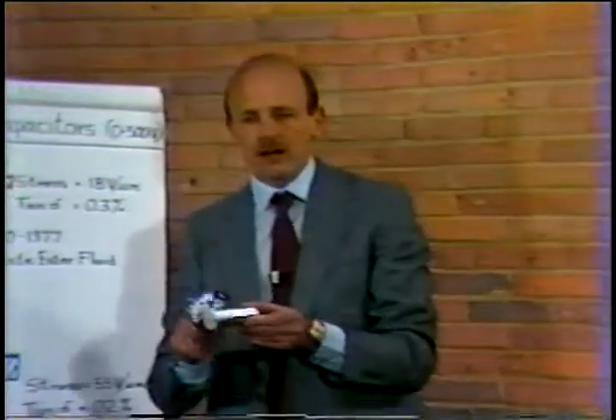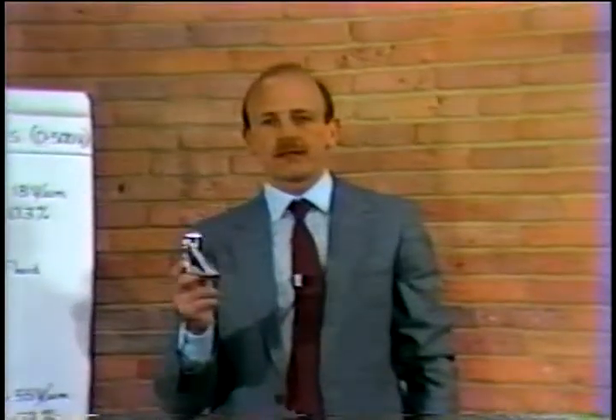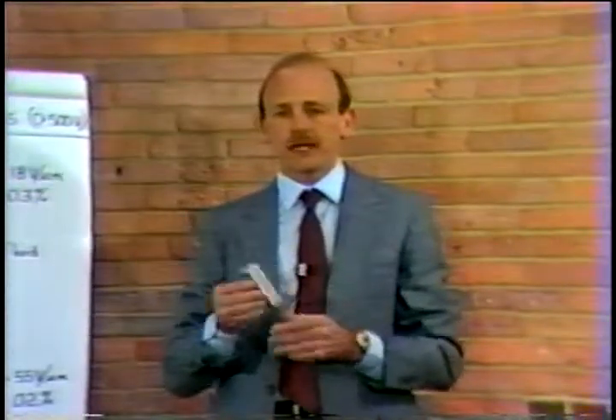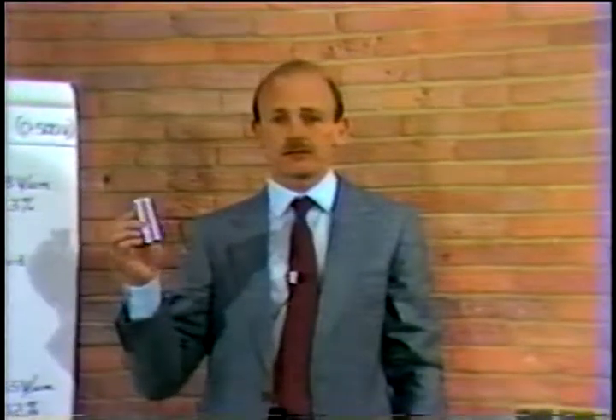During the winding process, it is very difficult to eliminate all the voids present in a capacitor roll. It is wound as hard and tight as possible, almost like a solid piece of plastic. But it is inevitable that there will be some voids present in this roll. It's further observed that during thermal cycling, the roll will expand and the outer part of the roll will become loosened. And as it contracts, it will stay in a loosened form. Voids can develop in the outer parts of these rolls. And at high voltages, especially above 500 volts, partial discharges become very important.